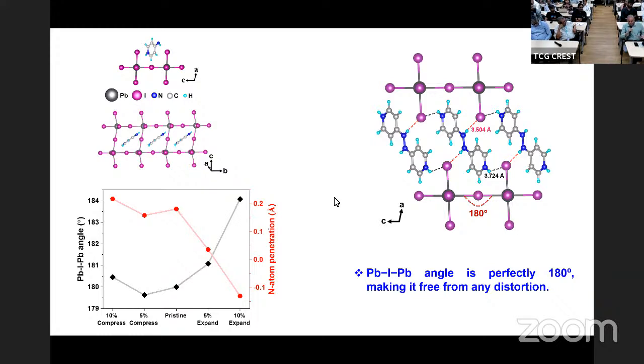This antiferromagnetic ground state is interesting for various reasons, including the multiferroicity context, the work by Nicola Spaldin on canted antiferromagnetism, ferromagnetism coming from canting. We are looking at a few such systems. You could have coexistence with ferroelectricity. The magnetic moment will be small, but you can still have it coupled, because of magnetocrystalline anisotropy. That's the design principle there. And we are looking at some of the systems.